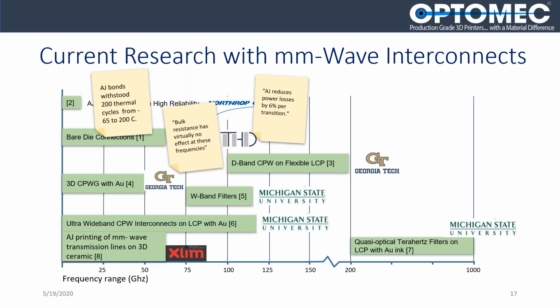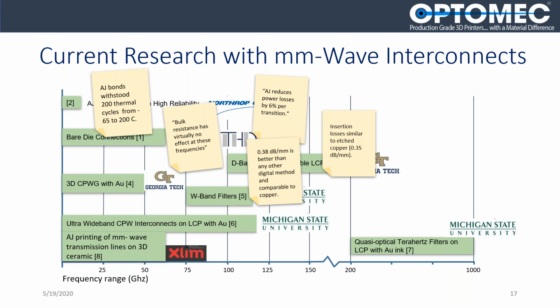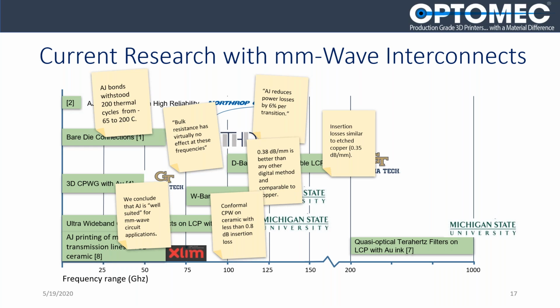Georgia Tech specifically measured roughly 6% better performance per transition with respect to power loss. Michigan State, comparing directly with copper, found that it is better than really any other digital printing process, with the way that we make our interconnects. Insertion loss is very similar to etched copper as we approach and exceed 110 gigahertz. Michigan State made the claim, we conclude that AJ is well suited for millimeter wave circuit applications. And for conformal coplanar waveguides on ceramics, XLIM measured less than 0.8 dB insertion loss. This is quite a valuable thing.